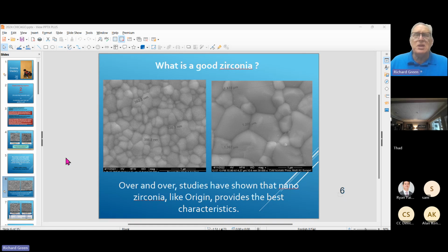You're sintering this stuff in about an hour with 25 units. That's really moving. And so as we go through the process, the hydro, or excuse me, the colloidal process that we use starts out with smaller grains. It's smaller grains in the green state. It's smaller grains in the sintered state, and all of those things contribute to lower activation temperatures and faster sintering, and it responds better.